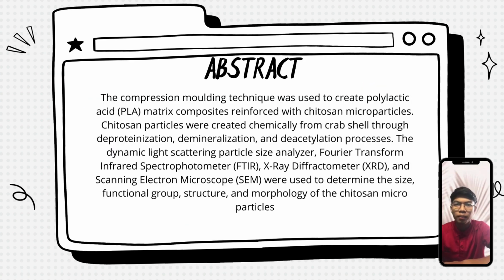Assalamualaikum. For the abstract part, the compression molding technique was used to create a polylactic acid (PLA) matrix composite reinforced with Chitosan microparticles. Chitosan particles were created chemically from crab shell through deproteinization, demineralization, and deacetylation processes. The dynamic light scattering particle size analyzer, Fourier transform infrared spectrometer (FTIR), X-ray diffractometer (XRD), and scanning electron microscope (SEM) were used to determine the size, functional group, structure, and morphology of the Chitosan microparticles.